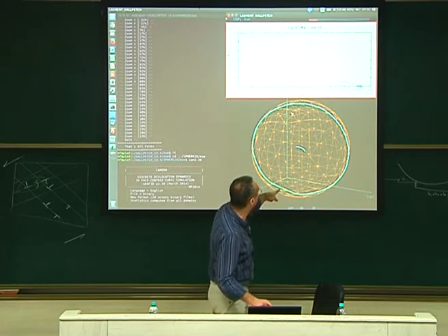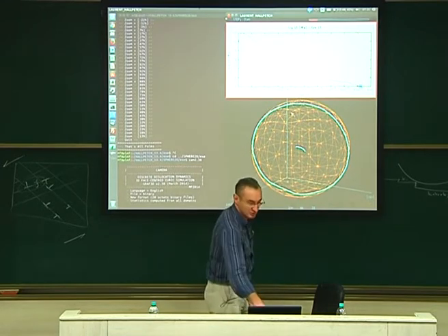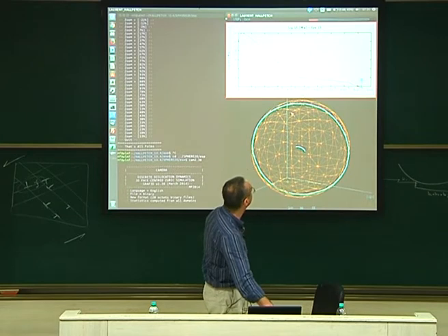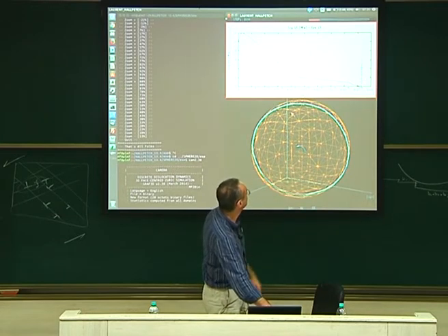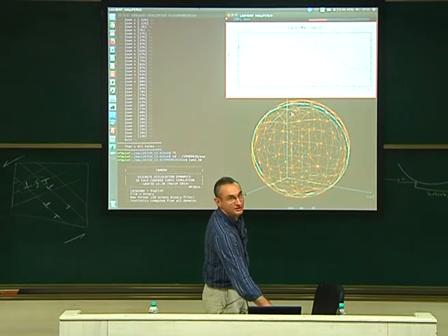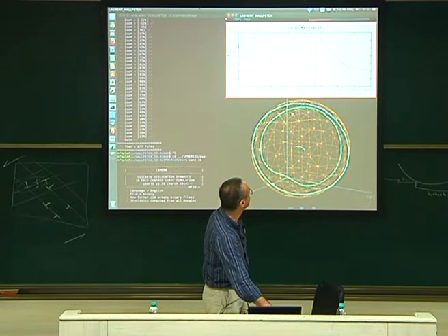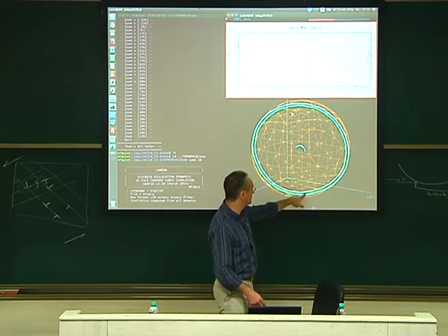And here now you need to apply more stress to activate the next, in order to get the same strain rate. So you will see the mechanism. The stress increases a lot, like this. The new dislocation will be nucleated, emit a new one, and go on and go on. And that way you have all the pile-up mechanism. You see? The dislocation coming up. So this is the pile-up. Here you have two loops.